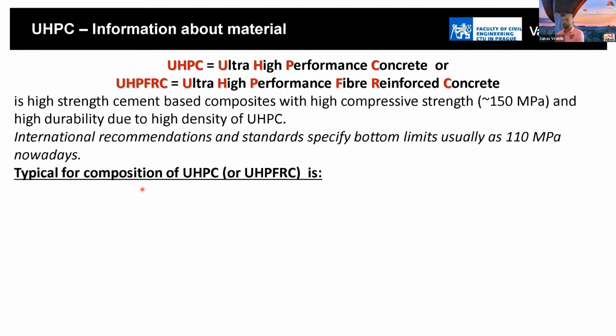The basic characteristic of this material is that it is a high strength cement-based composite material, but the advantage is not only high compressive strength. For example, typically we reach 150 megapascal, but also high tensile strength during bending, which is more than 20-25 megapascal. Also the tensile strength in pure tension is approximately 5 to 7 megapascal. But there are also non-mechanical properties besides the mechanical behavior of the material: the properties due to durability, maintenance, and basic behavior of the concrete.